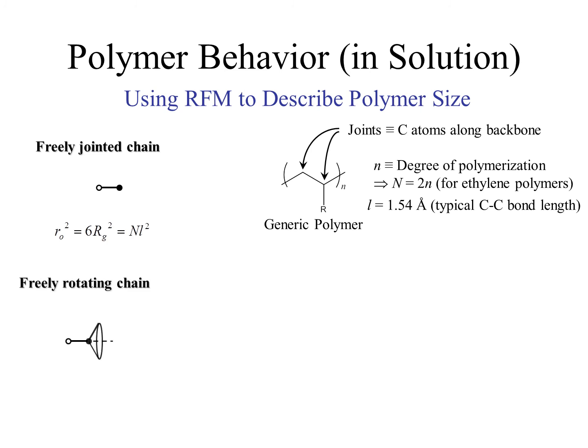As a better approximation, we also have what is called the freely rotating version. This takes into consideration that the direction a real carbon-to-carbon bond will take is dependent on the previous bond direction. Namely, this is because the sp3 hybridized bond angle is about 109.5 degrees, which means the angle which any segment may take must be 70.5 degrees from the straight ahead direction.